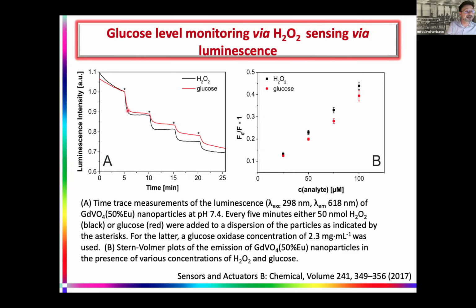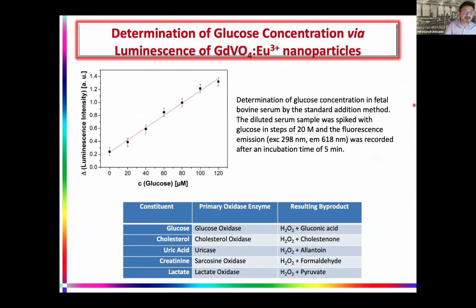And on the left side, you can see the example of the measurements where we, at the same time interval, add to one sample hydrogen peroxide, and to another sample where we put glucose oxidase, we add glucose. And you can see that the intensity of fluorescence follows the same pattern. Here's the Stern-Volmer plot. It's a little bit different because the reaction never ends, so it's exponentially approaching zero, but it's not a problem since you can always calibrate for this some element of incubation. You get excellent plot linearity, so you have a way that in a very simple manner you can detect the glucose from your sample by measuring fluorescence.